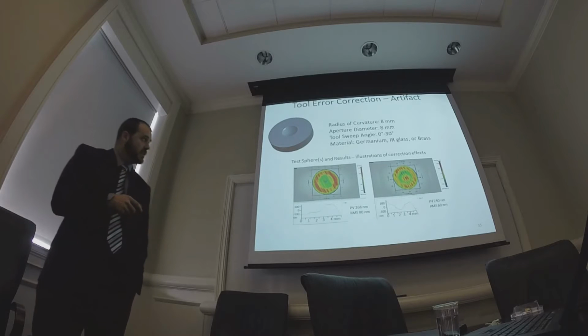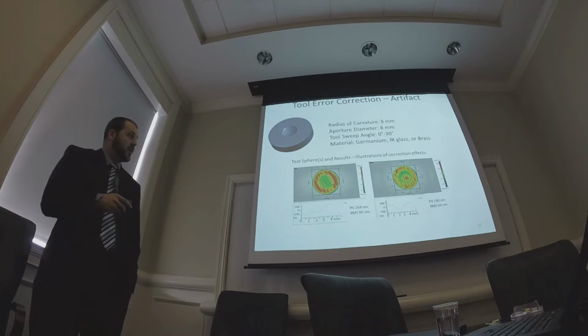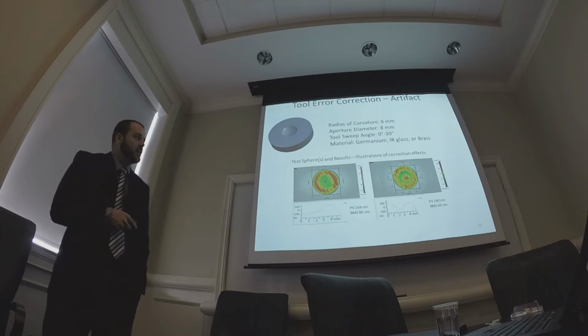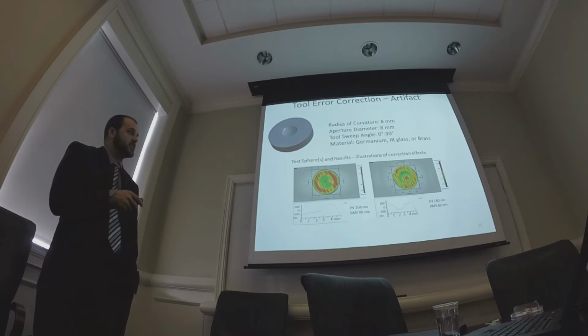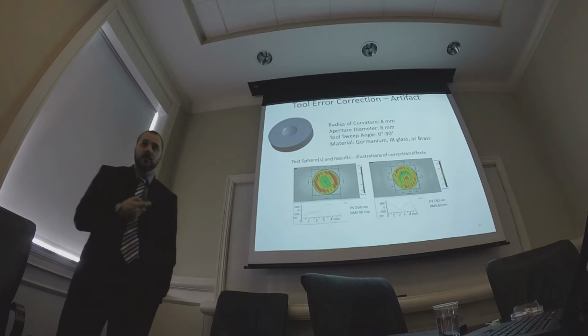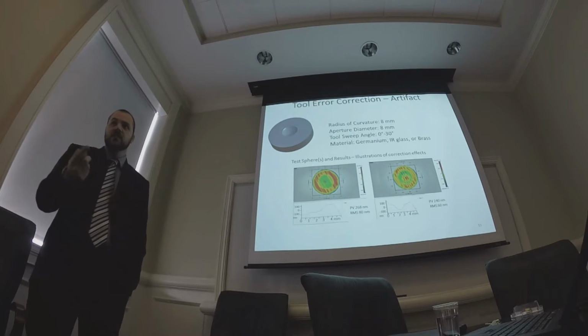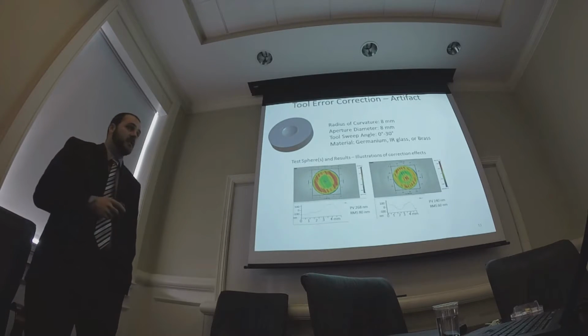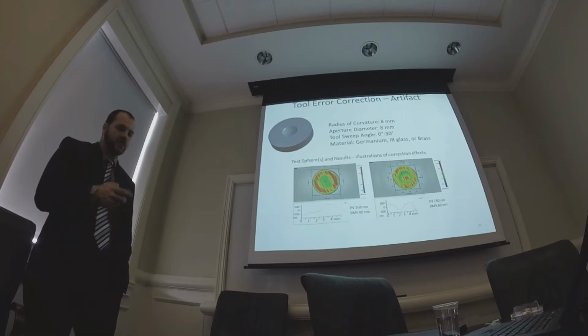Here's a couple of examples: we cut a sphere with no correction, then we made a change to the tool path. It didn't necessarily make it any better, but we made a change to the tool path, and we saw a change in the form. That lets us know that things are happening by adjusting the tool path based on tool shape, based on tool geometry.